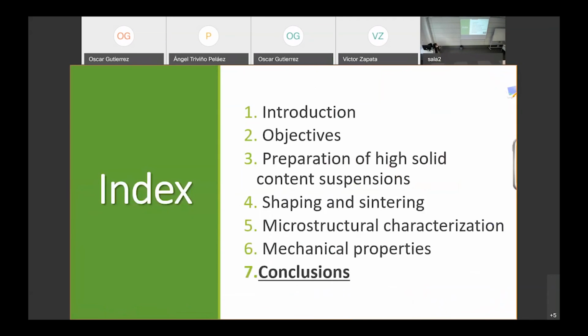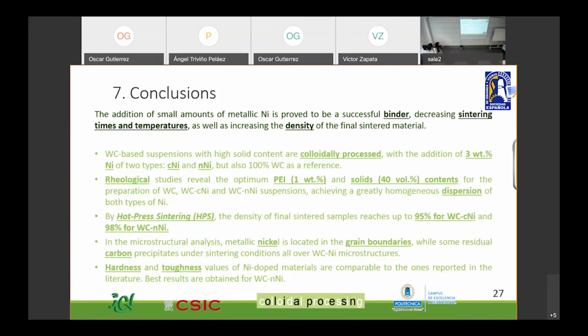So I would say that the main conclusion of this work is that the addition of small amounts of metallic nickel is proved to be a successful binder, decreasing sintering times and temperature, as well as increasing the density of the final sintered material. Tungsten carbide-based suspensions with high solid contents are colloidally processed, with the addition of just 3% in weight of nickel of two different types, a commercial nickel and a nanometric nickel synthesized in our lab, but also the binderless tungsten carbide material as a reference.